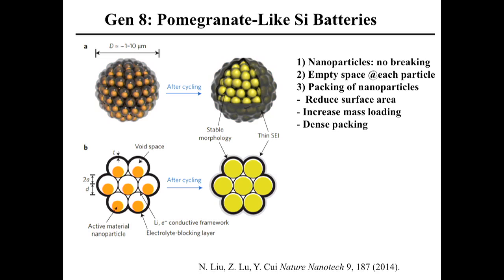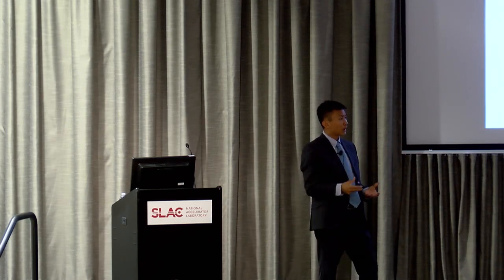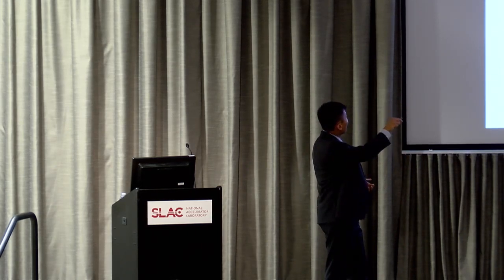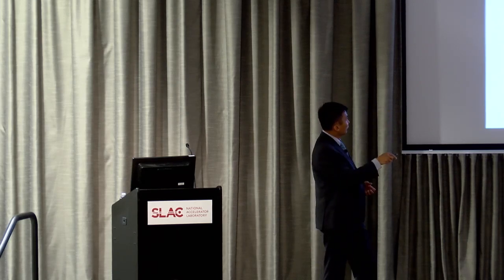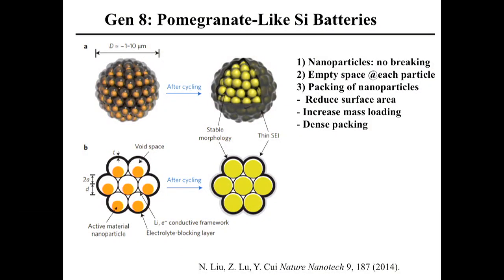So make sure this expansion doesn't crack your coating. We pack all these particles together, hundreds of thousands of these particles, forming a secondary particle like this. Why do we want to do that? That's because for an individual nanoparticle, the surface area to volume ratio is too big. They're going to react with electrolyte, consume too much electrolyte. Packed into a secondary particle, electrolyte only wets the outside. We reduce the surface areas. We are also having something called increased mass loading because we pack so much material together efficiently onto one electrode. So we can have more capacity to store lithium. And this helps dense packing, so the charge storage capacity per unit volume can go up.